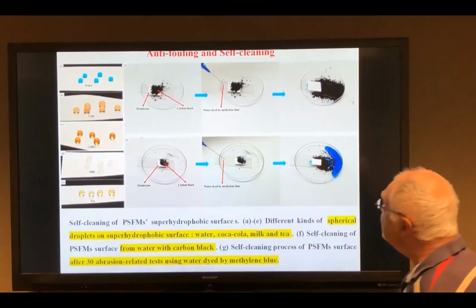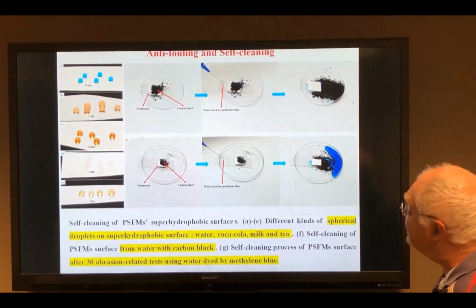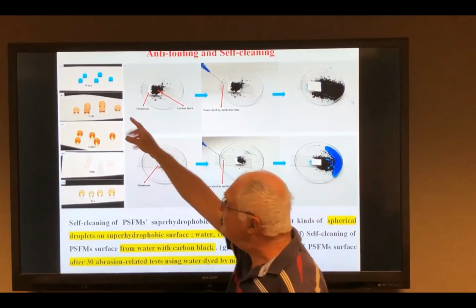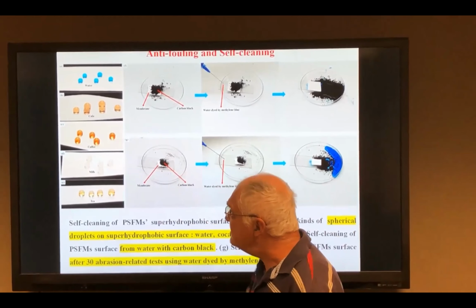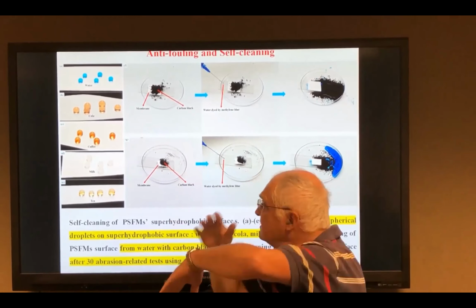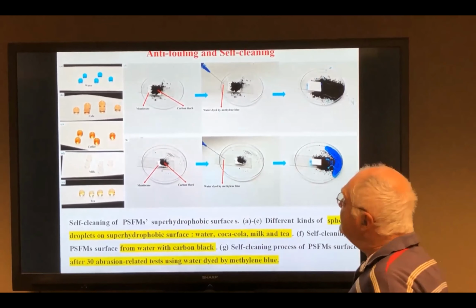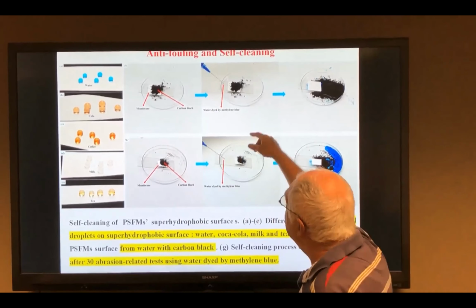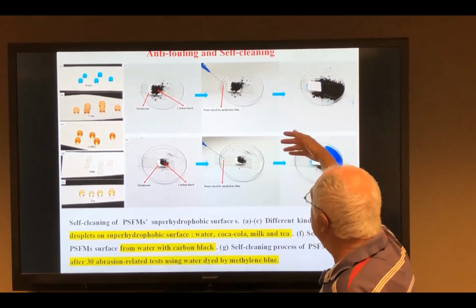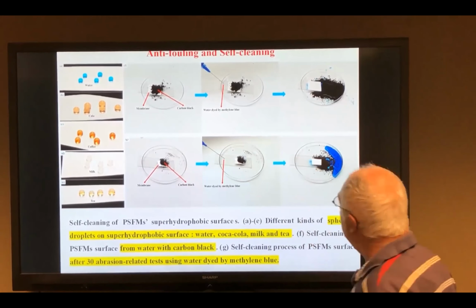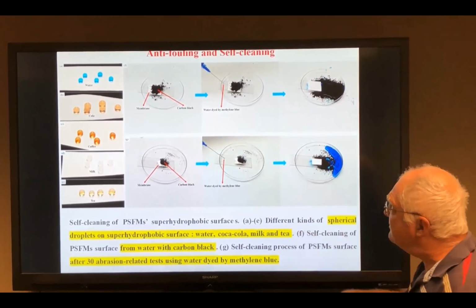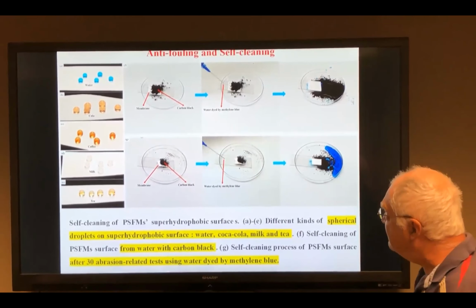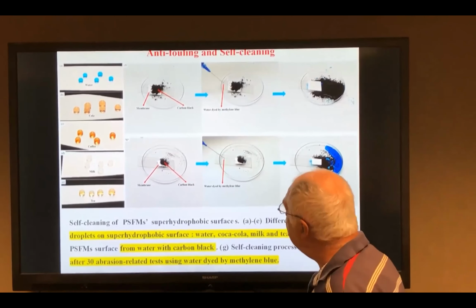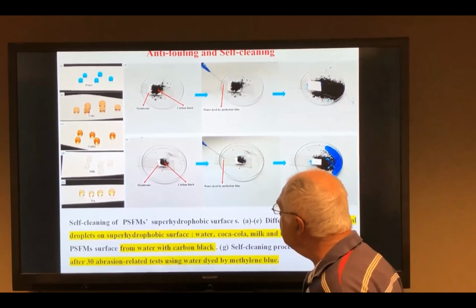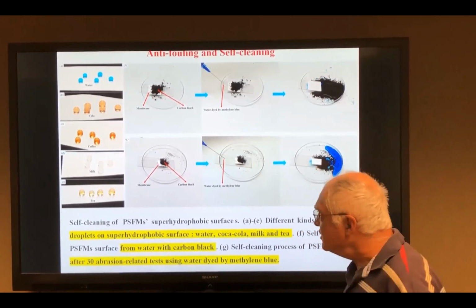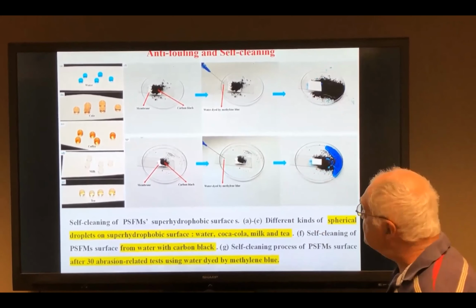And the next one is anti-fouling and self-cleaning. So you can put different liquids, droplets on top of this membrane, okay, and you just tilt it and they roll over. Then you can put, like, carbon black, and using a small water jet, you immediately wash it away. Okay, so you can do this even with membranes degraded by a abrasion test, and you're still good and self-cleaning. So all in all, let me come to my conclusions.